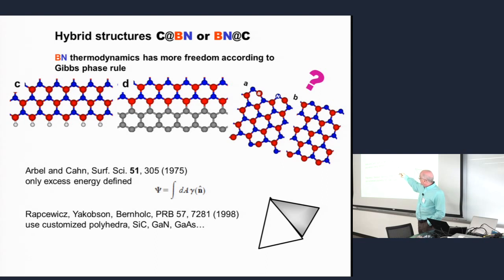Because on one side you have boron, on another side you have nitrogen. Clearly these edges are very different, and the average is just average. You cannot single out, at least this way, what is edge energy, and then you cannot do many things because of this.